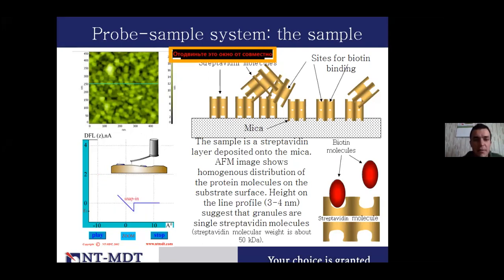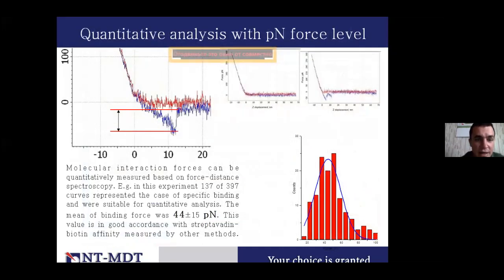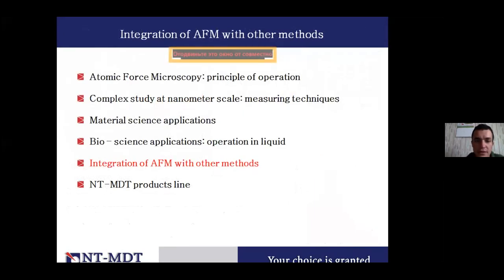By doing this approach and retraction at different points, we can measure this curve on the bottom left and then make some statistical data analysis. From this statistical analysis, we can calculate exactly what this binding force is, since we know the stiffness of the cantilever, which is deflecting during these measurements. From this statistical calculation, it appeared to be about 44 piconewtons, which accordingly fits the theoretical data for the interaction of these two molecules. So this was about the single molecule interaction application.